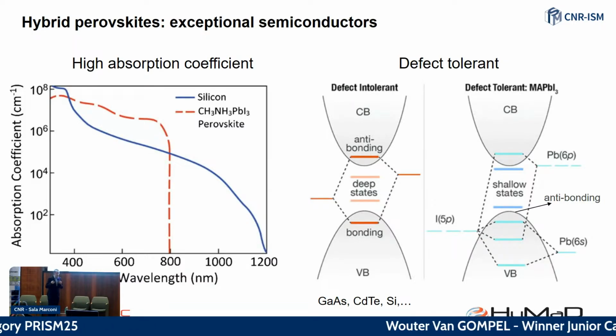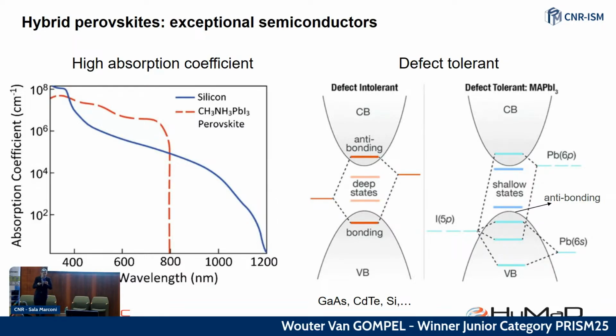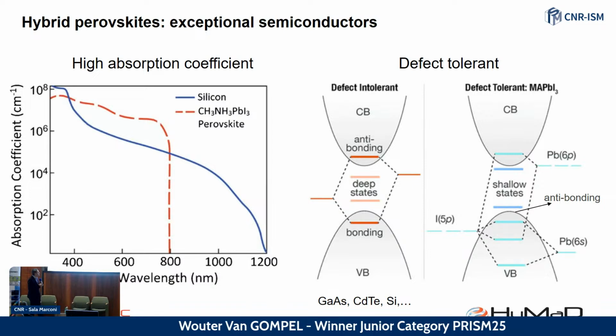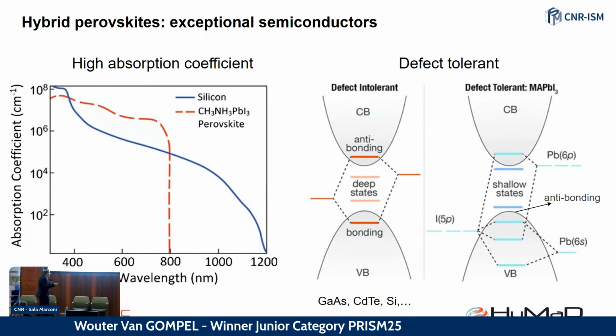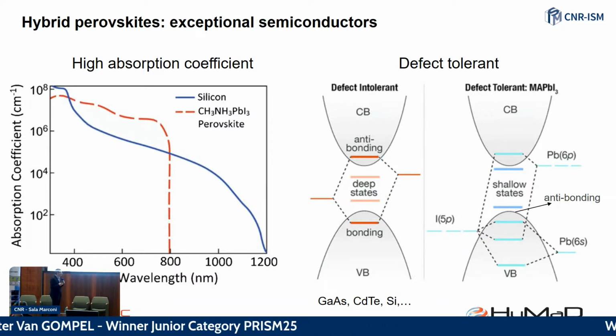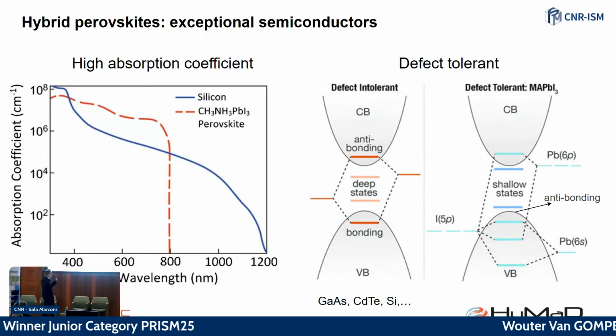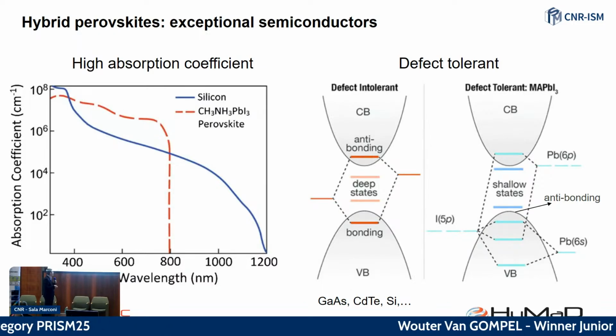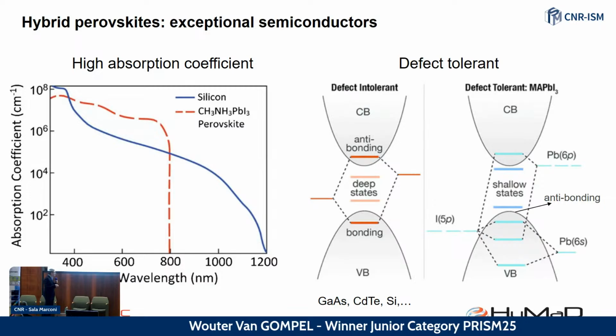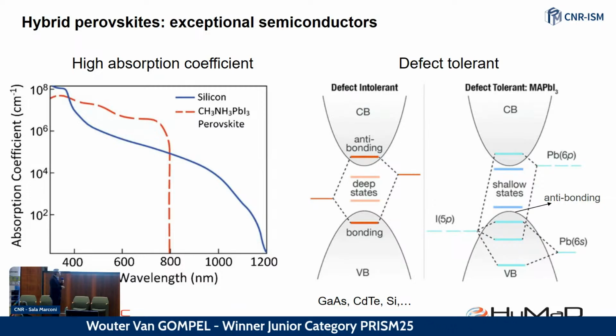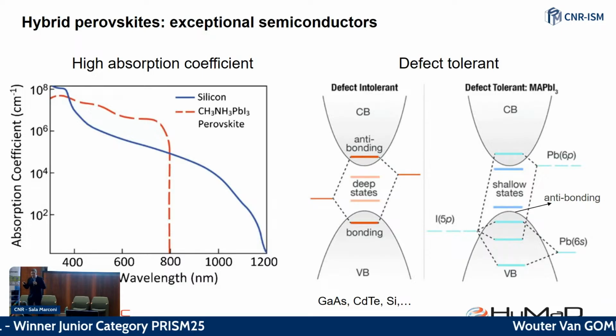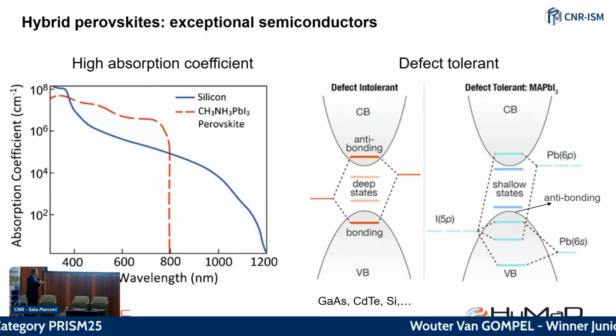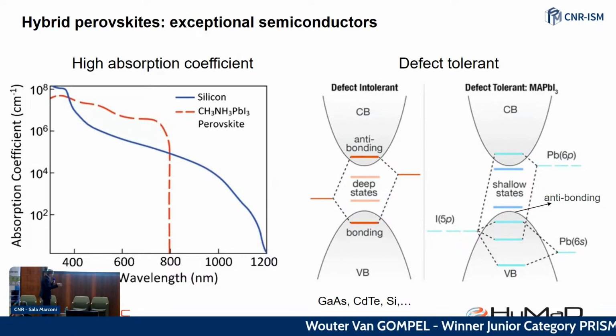So that's one of the reasons why you do not really need to use a clean room to get a very nicely working device. The processing conditions can be quite dirty, let's say, especially compared to telluride, silicon, and so on, and still give very highly functioning semiconductors. So that's really a huge advantage. Of course, typically the devices still work better if you eliminate as many defects as possible at surfaces and things like that.